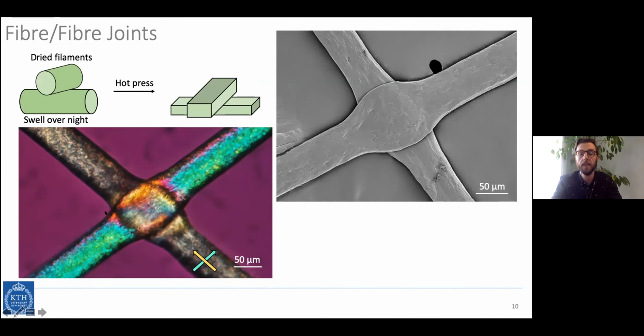If we take a look in the SEM, we can see a similar joint. A couple of things to note: when we hot press these filaments together, they compress and flatten out, as you'd expect for a regular fiber joint. And we can very accurately measure the interfacial area between these joints.